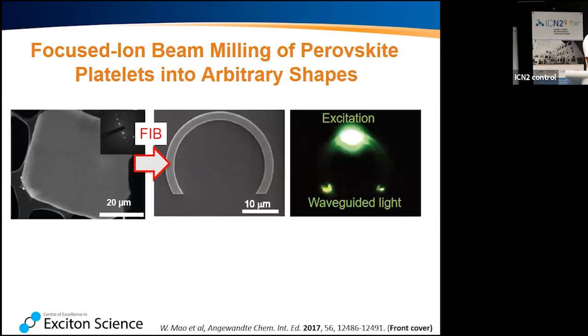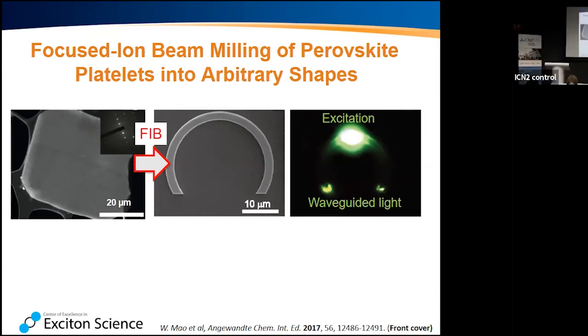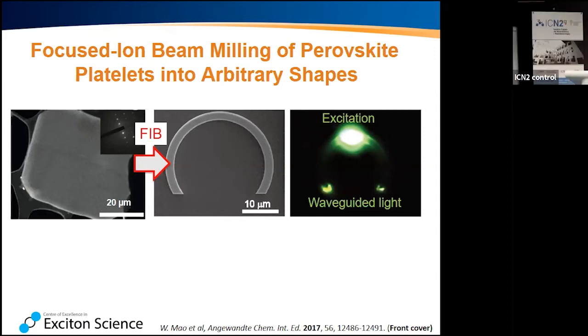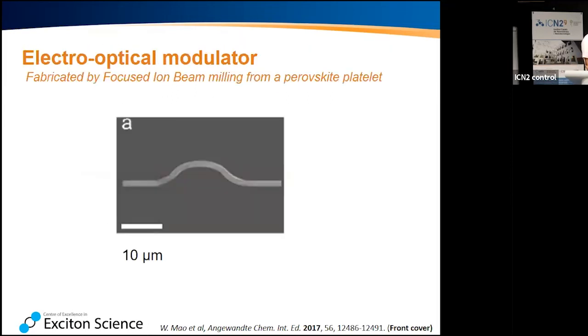One thing we did, we used focused ion beam milling. So we took one of these platelets and then cut a ring out of it. So this ring comes out of a single crystal. And what happens is if you excite the center here, you can see there's some wave guiding going on, and whatever fluorescence you create inside your material goes wave guiding and reaches the ends of your circular structure. And we had a similar structure here.